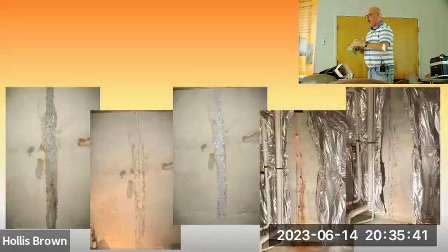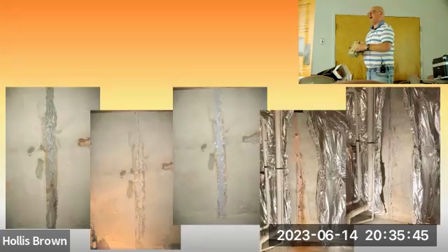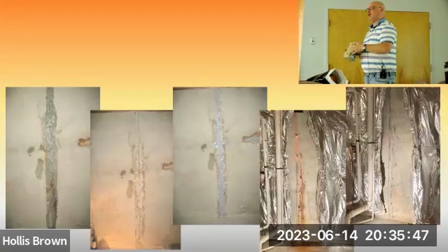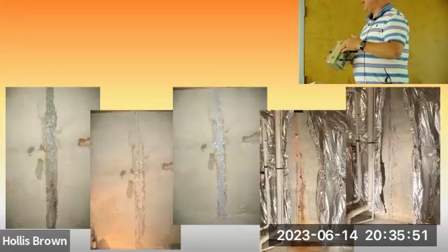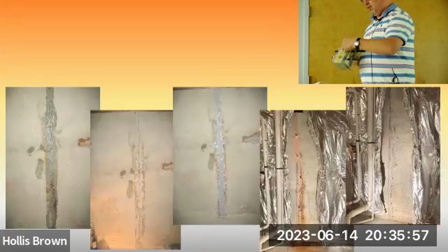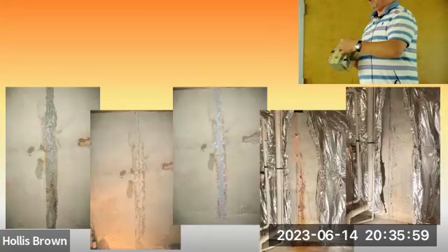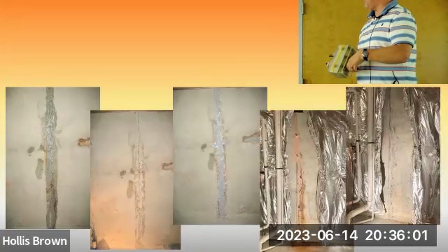I cauterize the surface. I don't just put on the epoxy. I go with a torch and a trowel, and I cauterize it. And the reason I do that more, it forces you to take a second look at it before it's too late, to make sure you don't have any pinholes for the material to shoot out when you're injecting it.